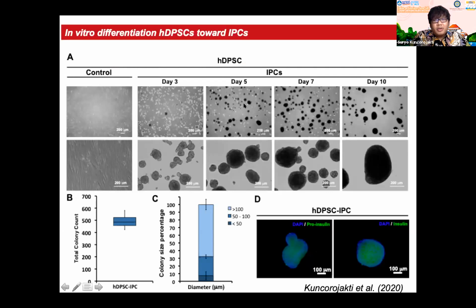Dr. Watchareewan already mentioned the induction protocol and the results. And here are the results using the 10-day induction protocol that we used in this study. We just used a 3-stage induction protocol. The initial differentiation was observed at day 3, where the single suspension of stem cells at day 0 changed into cell aggregates, or cell colonies. Further development of the cell aggregates was observed at day 5, day 7, and day 10 at the end of the experiment. At the end of the induction protocol, big and dense cell aggregates were observed.